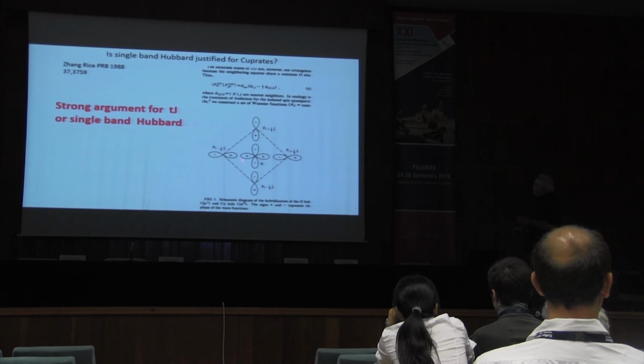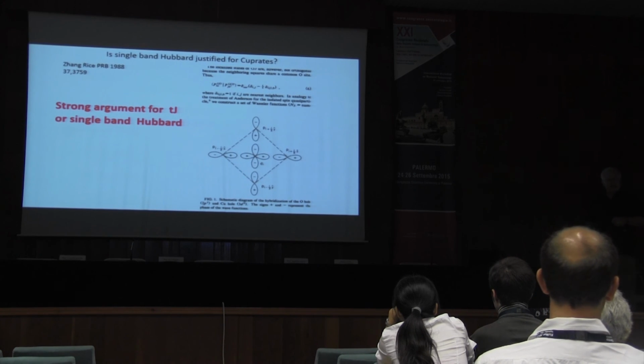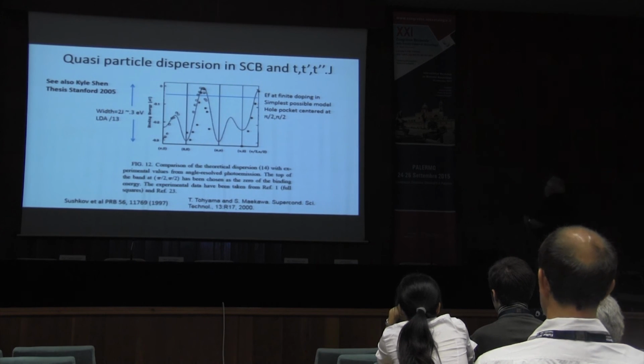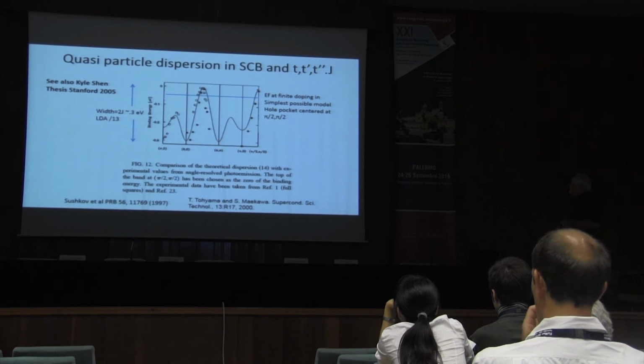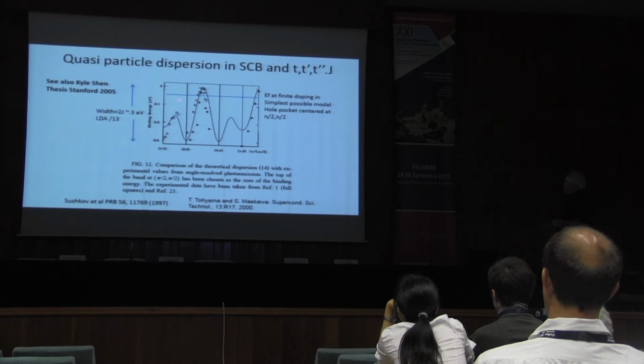Now, once you have that and say that, well, this is the right story, then actually you could go back to a single band Hubbard-like model because it looks like that, right? You again made the spin 0 on the copper effectively by adding that extra hole. Now, that story, indeed, many people work with single band Hubbard models and with t-J models and so on, and indeed, it gives you a very nice agreement with the experimental dispersion that you measure with angle-resolved photoemission. Okay, so this is actually done in an approximate way. This is in a self-consistent Born type of approximation, but it seems to work very, very well.